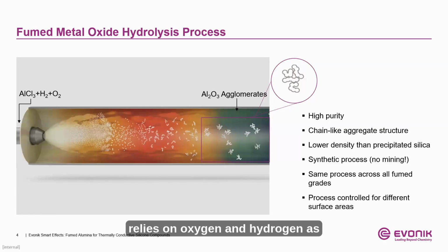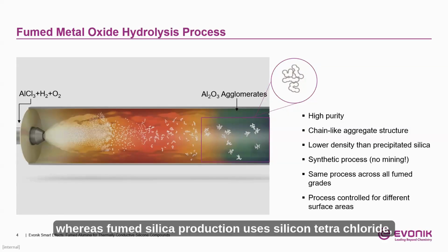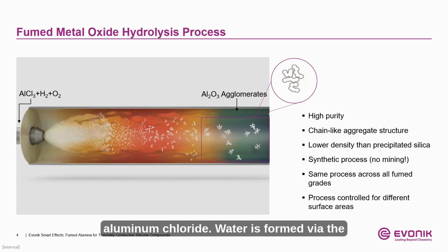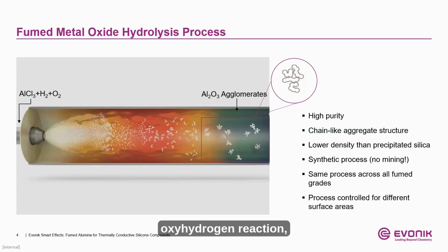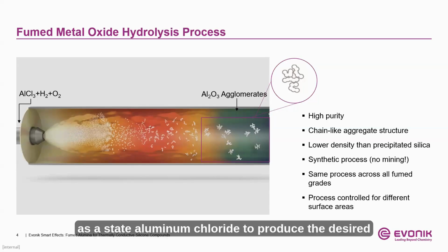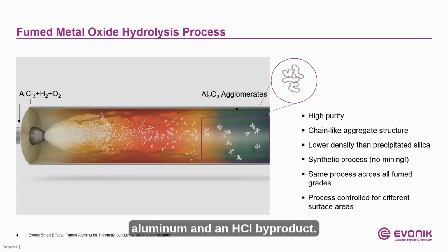It relies on oxygen and hydrogen as reactants. However, whereas fumed silica production uses silicon tetrachloride, the fumed alumina production uses aluminum chloride. Hydrogen and oxygen are reacted in the presence of the aluminum chloride. Water is formed via the oxyhydrogen reaction, which then reacts with gaseous state aluminum chloride to produce the desired alumina and an HCl byproduct. Once the product is cooled, a deacidification step is performed to clean the solid state aluminum